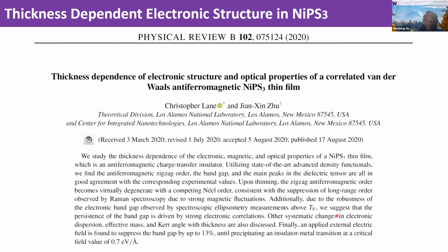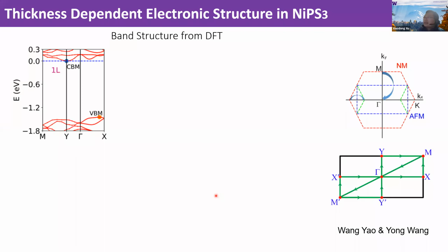At the time when we had our results and wrote up the paper, we also found there's a theory paper online, eventually published. This theory, basically DFT calculations, already reported the thickness-dependent electronic structures and optical properties in these nickel phosphorus trisulfide films. They found that the optical anisotropies and the electronic structure have a strong layer dependence. I'm not going into details of these calculations, but what I present to you is the calculation done by my collaborator, and it is essentially similar to what's published.